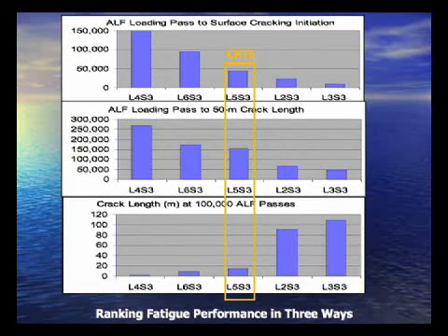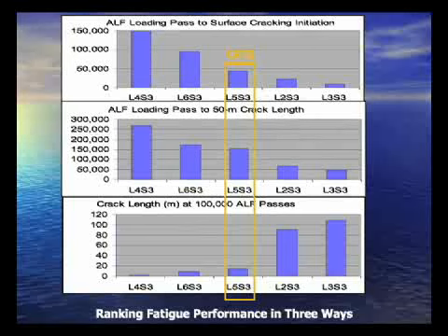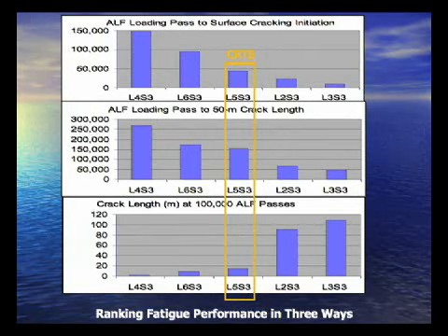So, it tells the same story, whichever way you look at it. Passes to surface crack initiation, that's when we see it on the surface. This is the ranking we see here. Passes to a 50-meter crack length, that's what we see there. And it's the same ranking here. And then crack length at 100,000 passes.